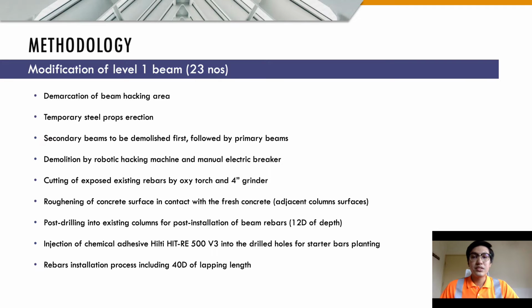Roughening of the concrete surface in contact with the fresh concrete is required for concrete-to-concrete bonding. In this case, the adjacent column surfaces in contact with the modified beams are roughened. Concurrently, the post-drilling process into the existing adjacent columns was started for the post-installation of beam rebars. The depth of the post-drilling work is 12 times the required bar diameter, which is also known as 12D.